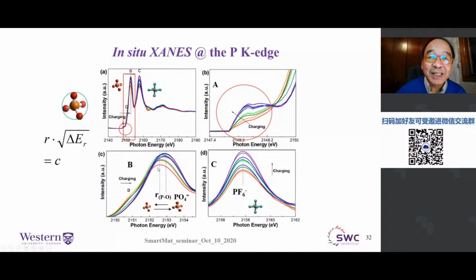Charging, discharging, and you can really see it. The maximum changes, and according to the theory, this maximum has to do with the distortion, right? So that bonding changes. Okay, normally, if the maximum shifts away from the threshold, that means it gets shorter. If it shifts close to the threshold, it gets longer. Okay, so this example actually gives you an illustration of how X-ray absorption can be used to track chemical and dynamic changes in a lithium-ion battery during the run.